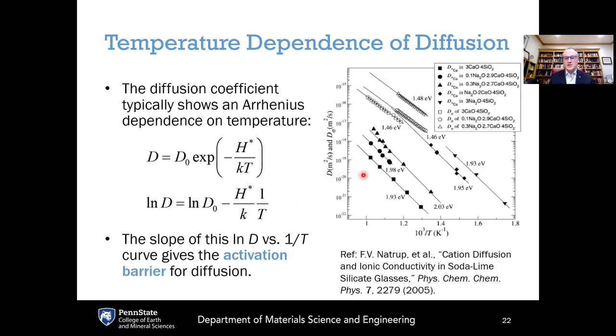This plot on the right shows you an example of the diffusion coefficient plotted on a logarithmic axis versus inverse temperature on the x-axis here. And what you will see is if you plot the logarithm of the diffusion coefficient versus inverse temperature, in most cases, that will give you a straight line. And that is what's known as an Arrhenius dependence. So anything where you take a transport property like diffusion coefficient, plot the logarithm of that versus inverse temperature, if you get a straight line, that is indicative of an Arrhenius temperature dependence.